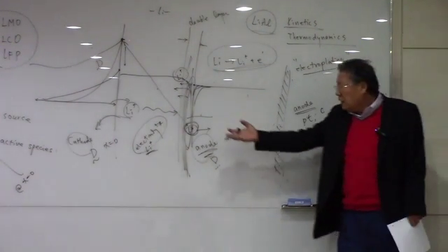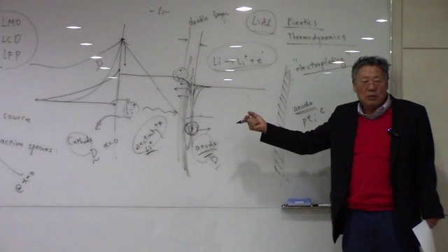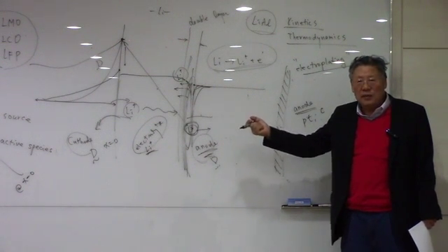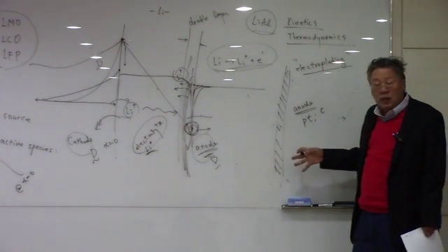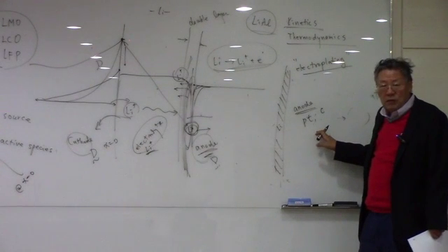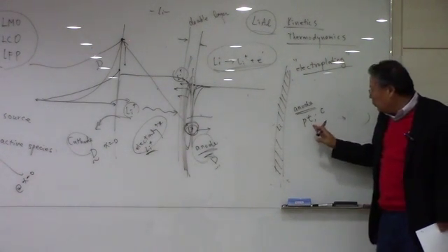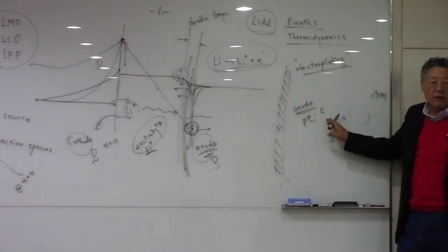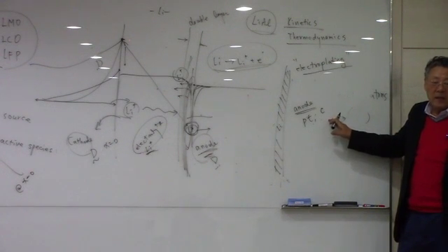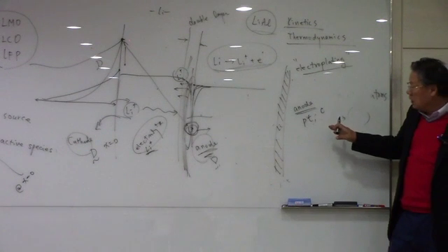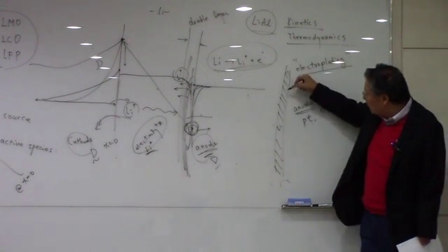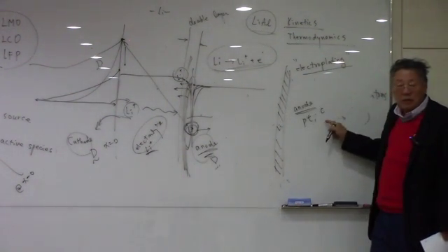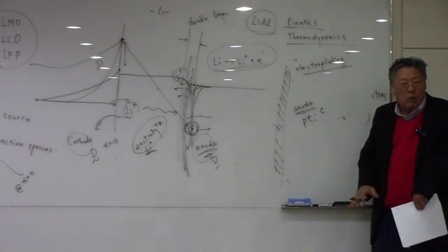And then we take lithium out from the cathode and put the lithium into the anode. And this platinum and this graphite cannot accommodate the lithium. In other words, the diffusion coefficient of lithium into these materials is very, very low, let's suppose.